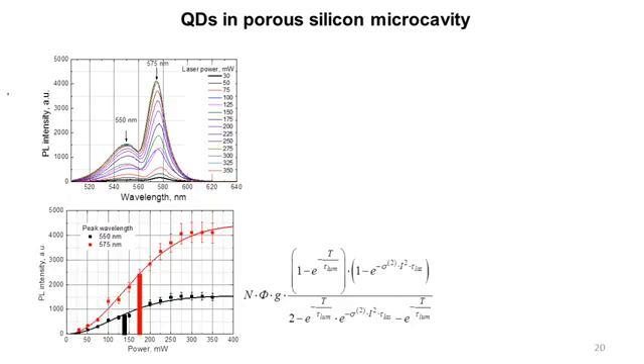In the bottom figure we have plotted the dependencies of peak intensities on the pump power in order to indirectly demonstrate that these two peaks have different radiative relaxation rates. As we increase the pump power, the initially quadratic dependencies saturate and the saturation threshold was higher for the long wave peak. We approximated the experimental dependencies with the presented equation and found that the observed difference in the saturation thresholds can be only a result of the significant change in the radiative lifetime.